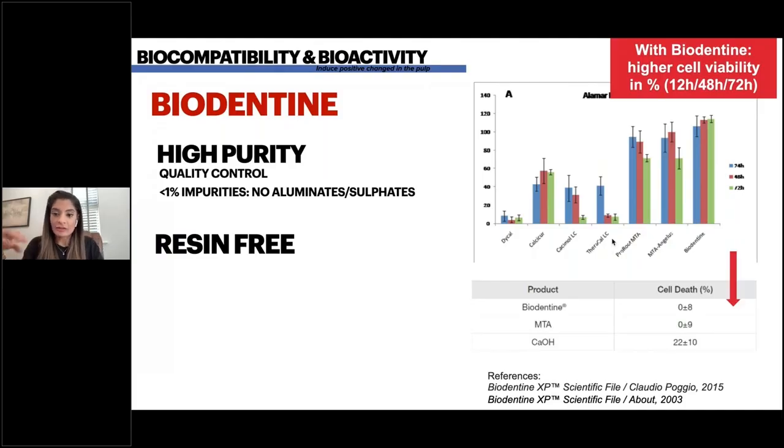So the benefit of having resin in a pulp capping agent is that it's easy to handle. So you pop the pulp capping agent there, you cure it, and then you can move on and do your final restoration. But we talked about how much damage resin can do to the actual pulp. So in an ideal world, we don't want that sort of material there. On top of that, when you cure with a light cure, you produce heat, and that can cause pulp damage, and you get some polymerization shrinkage as well, which is not ideal.